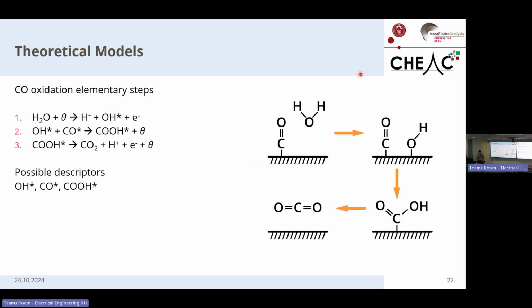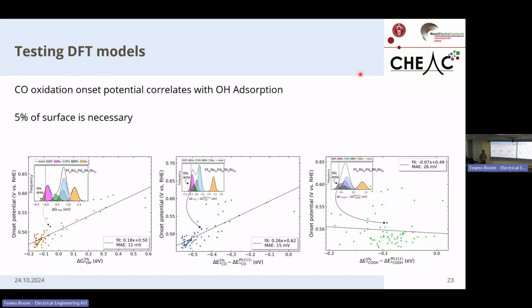We can look at the OH binding energy, the CO binding energy, and the COOH binding energy. And how do we know which of the descriptors is correct? For that, we can compare it again to our experimentally obtained data set and see which of these models best replicates the mathematical landscape that we have in our experiments. And now we see that the binding energy of OH has the best reproduction of our experimental data set.